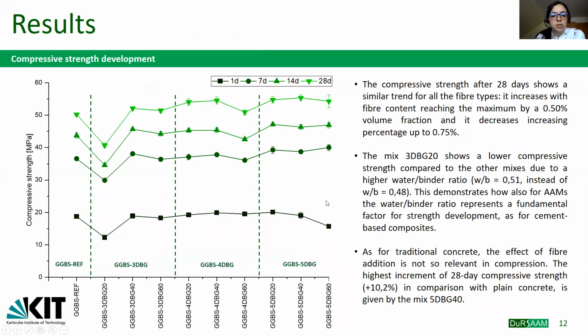The results of the compressive strength are shown in this diagram. As you can see, the compressive strength increases from 1 to 28 days for each mix. And also the compressive strength after 28 days shows a similar trend for all the mixes investigated. In fact, the compressive strength increases with the increase of the fiber percentage from 0.25 to 0.50, but the compressive strength decreases with an additional increase of fiber content from 0.50 to 0.75% volume fraction.